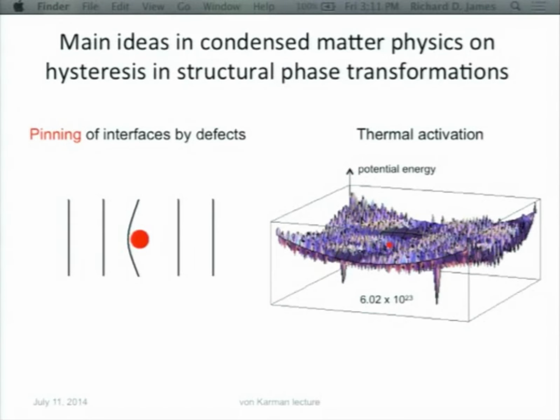It may even be at a local maximum of the potential energy, many people believe. Then as you lower the temperature again, it falls back into this well. But as you can imagine from this picture, the temperature at which it falls back into this well, because it has to find that well in this very wiggly surface, should be quite different from the temperature at which it finds its way out of the well. And that's the thermal activation origin of hysteresis. By the way, that does need to be worked out in this context.